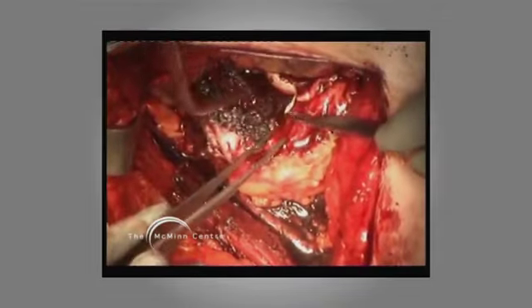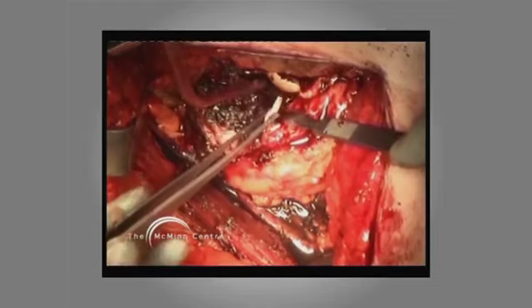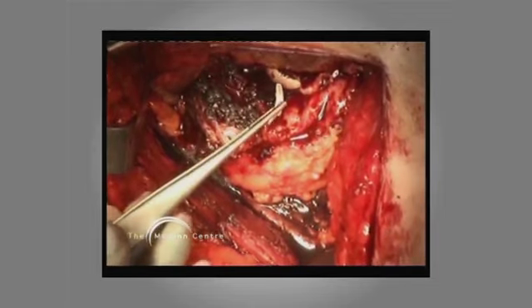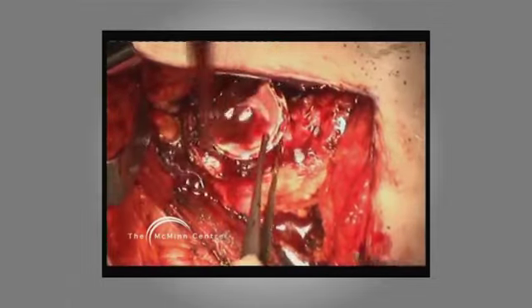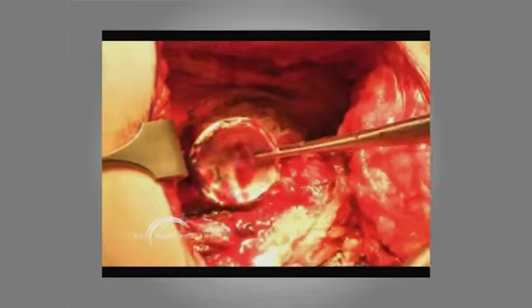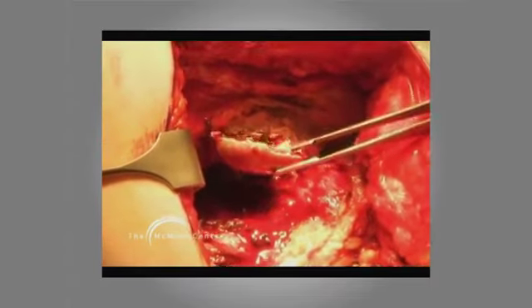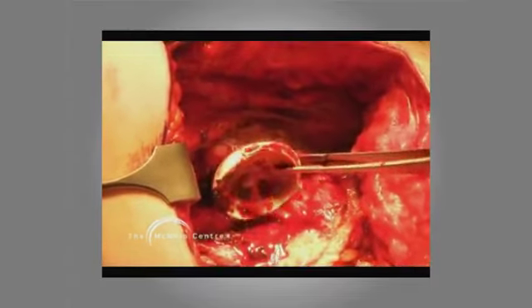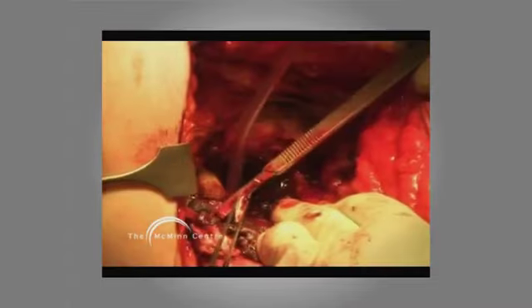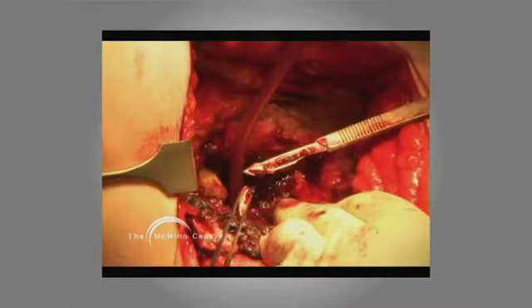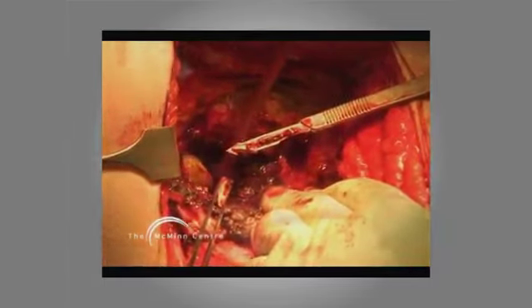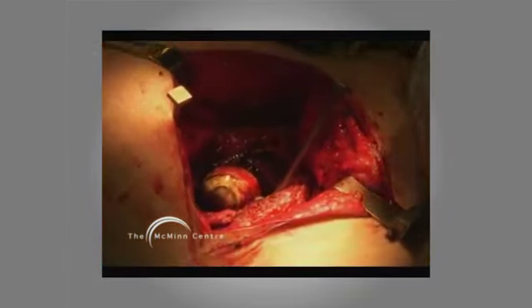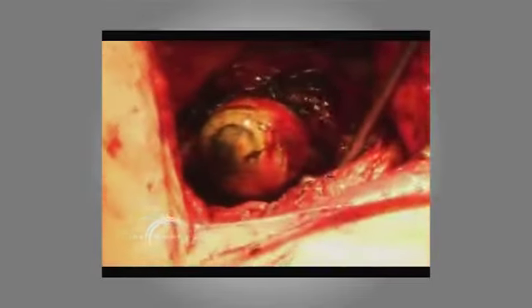And there's bits of broken ceramic, and there's the ceramic liner, and you can see that all around the rim of that thin liner it's been fractured and then dislocated. More bits of broken ceramic. There we are, dislocating the joint, and the ceramic coated head has worn through to the underlying metal.